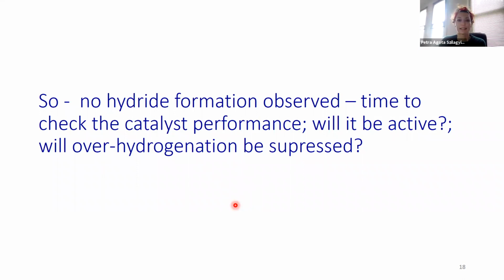And then we were looking at the actual catalyst performance. So we first checked whether it's active at all or not. And this is really just a quick test at room temperature. So at this point, the butadiene hydrogen mix is allowed on the sample, and we measure with a mass spec what's coming out of it. And as you can see, the butene formation was evident.